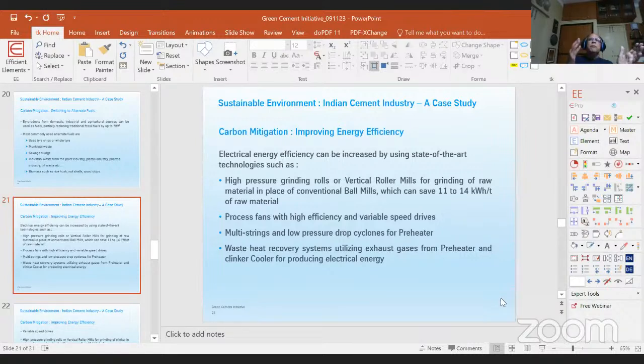You can go with the peripheral equipment, and the main peripheral equipment which controls the cement process is the process fans, the preheater exhaust fan, the cooler exhaust fan. That is available with high efficiency. Today we are talking of fan efficiencies of 82, 83%, which in former times was around 70, 74%. So 6 to 7% more saving on the fan power can be achieved these days. You can use variable speed drives to optimize the pressure and the volume combination, and then optimize the power consumption.